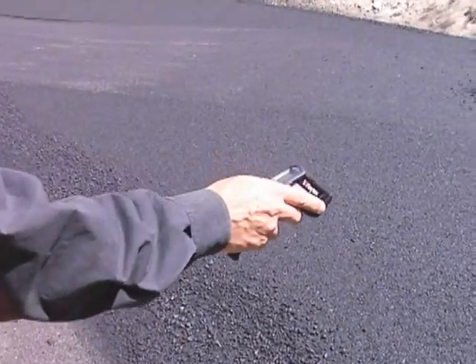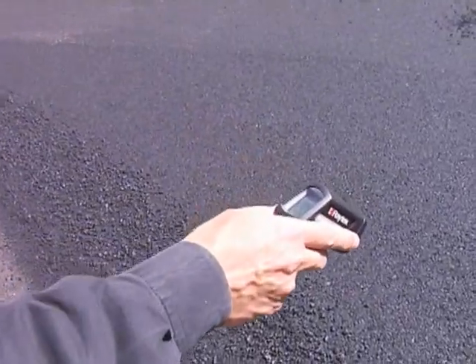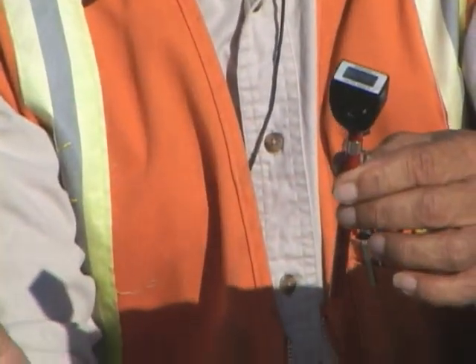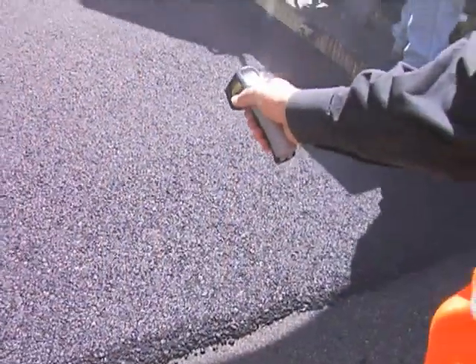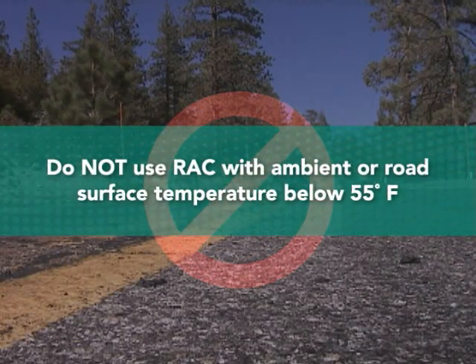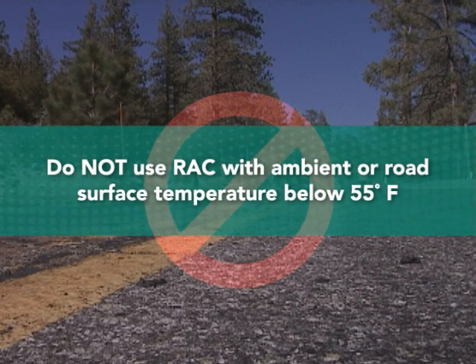RAC mixes and laydown temperatures should be monitored using infrared and stab thermometers. These devices should be calibrated on a regular basis. RAC should not be placed with an ambient or road surface temperature of less than 55 degrees Fahrenheit.